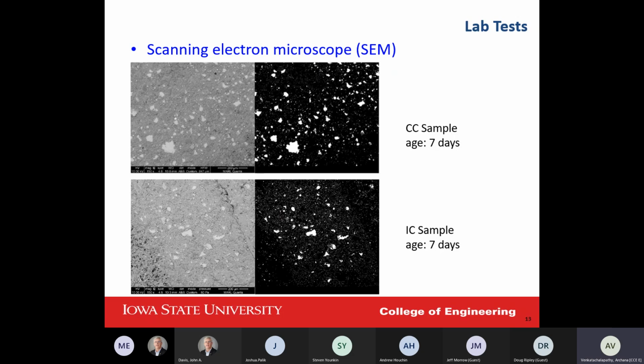As we can see, we analyze the pictures to measure and compare the white pixels, which means non-reacted cement. In the internal curing method, we have fewer non-reacted cement particles, but in the normal concrete, we have more. And yeah, that means it works.